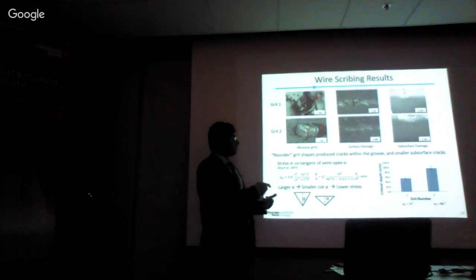When we correlated these results with existing literature, we find that the stress produced by the indenter shape depends on the cotangent of the semi-apex angle alpha. So if this is the apex of the indenter, a larger alpha will happen for a rounder grit shape, and that will give a smaller value of cotangent of alpha and a smaller stress. This means when you compare the critical depth of cut at which the first crack appears, we found the rounder abrasive shape, which has a larger value of semi-apex angle alpha, produced a higher critical depth of cut. It went to a larger depth before the first crack appears because the stress produced by this abrasive in the silicon material was lower compared to the stress produced by the sharper abrasive.